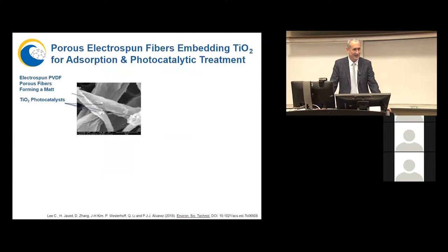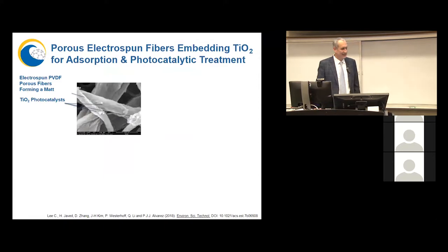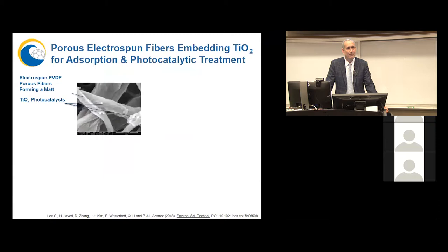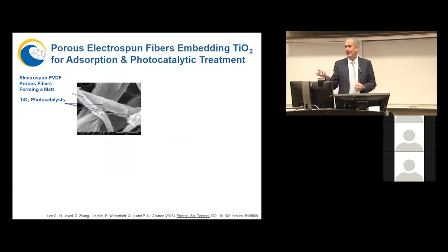immobilize titanium dioxide. In this example, we're using electrospun porous fibers that are weaved into a mat. And they're porous so that you can have better access of the pollutant to the embedded TiO2. And the idea is to, again, attract this polymer. It's somewhat hydrophobic. It's fluorinated so that it can resist oxidation by ROS. And it can attract moderately hydrophobic compounds, absorb them close to photocatalytic site, and destroy them right there.